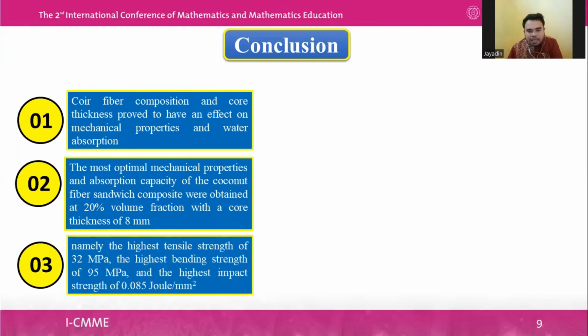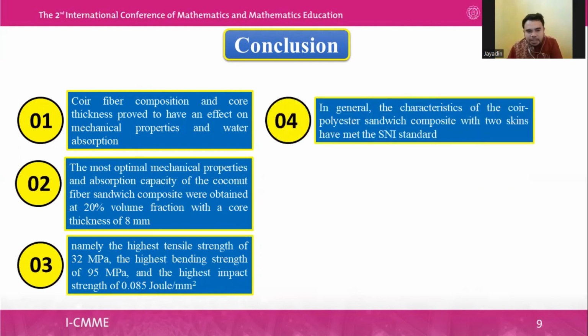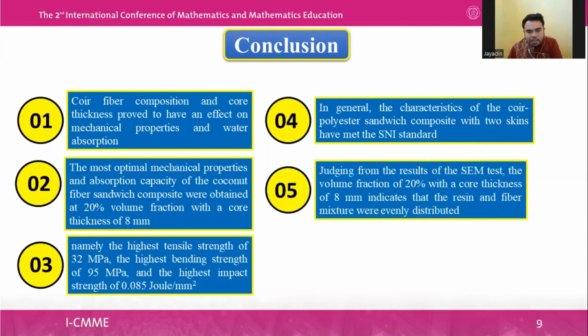namely the highest tensile strength of 32 megapascal, the highest bending strength of 95 megapascal, and the highest impact strength of 0.085 joule per square millimeter. In general, the characteristics of the coir polyester sandwich composite with skin have met the Indonesian national standard. Judging from the result of the scanning electron microscope test, the volume fraction of 20% with a core thickness of 8 millimeters indicates that the resin and fiber mixture were evenly distributed.